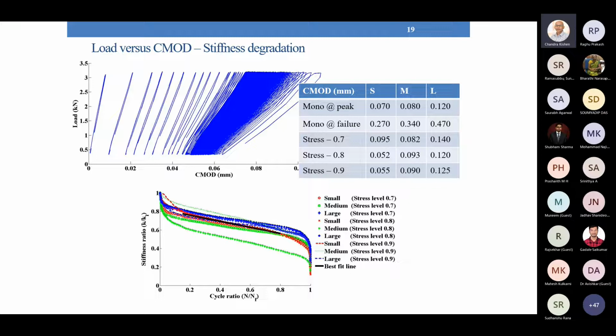And then in this table, what you see is the crack mouth opening displacement in millimeters. This is for small, medium, and large beams. The first row here is monotonic at peak. So what we see is at the peak load, in a monotonic test, these are the crack mouth opening displacements. At failure, as I told you earlier, in a monotonic test, the crack mouth opening displacements